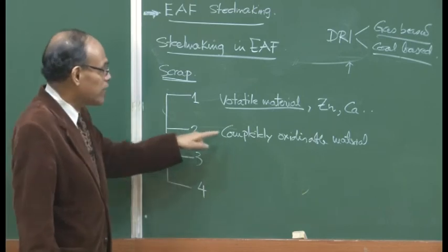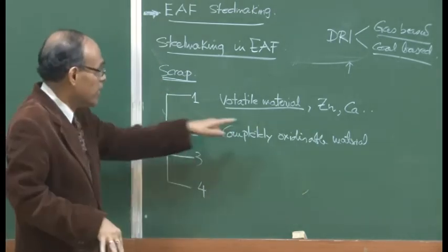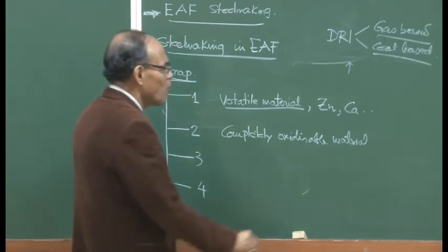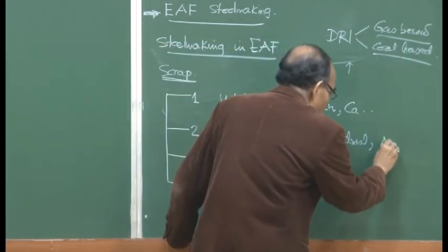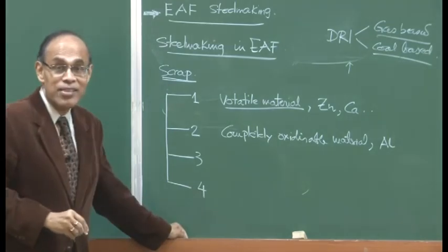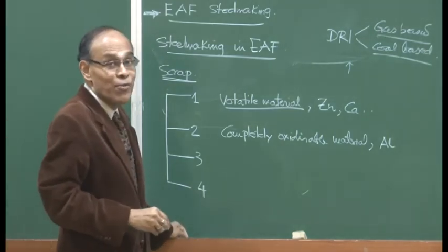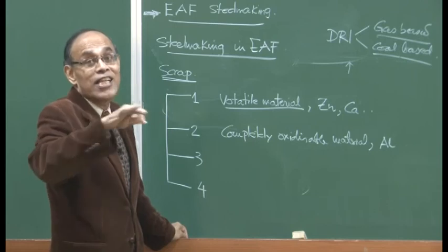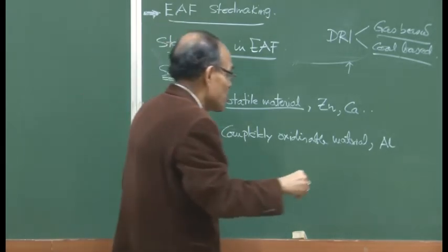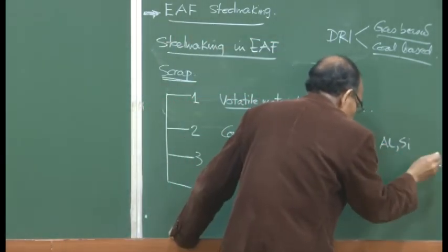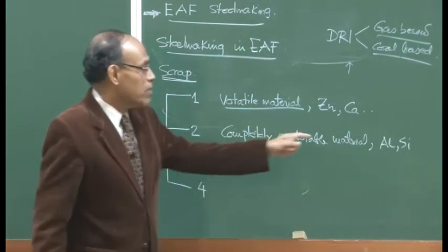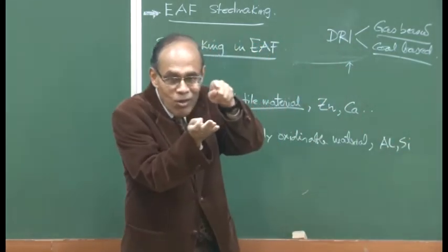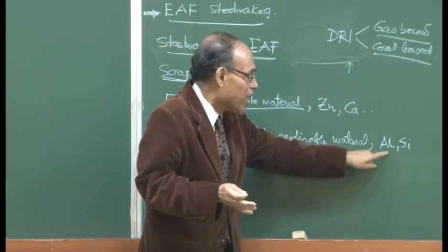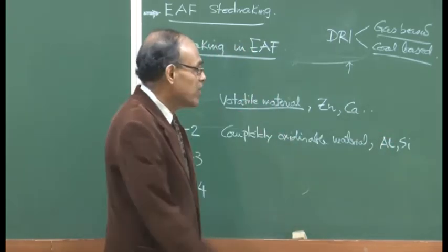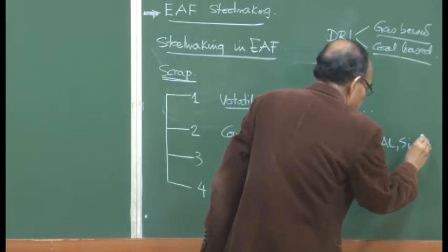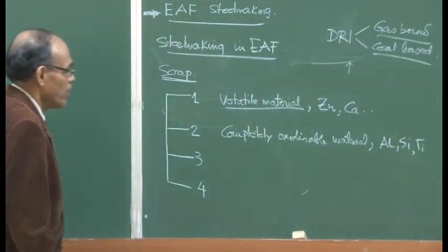Category 2: we are sorting the scrap containing completely oxidizable material, and completely oxidizable material we can say aluminum is one material under steel making condition, and we have seen that under steel making condition all silicon, from the silicon removal curves possibly, and we can add all those elements whose position in the Ellingham diagram is between the aluminum and silicon line. Possibly we can say titanium is also one more.